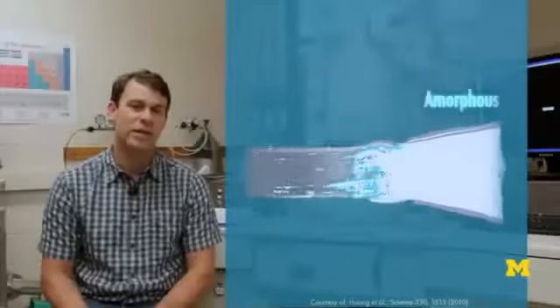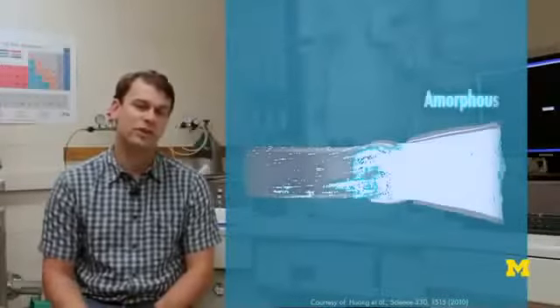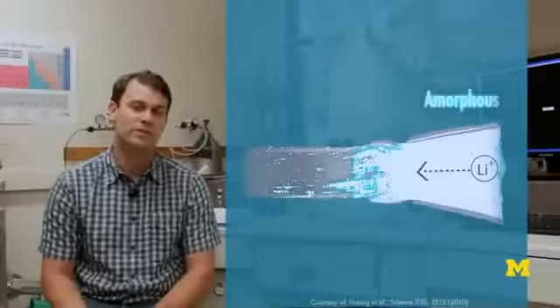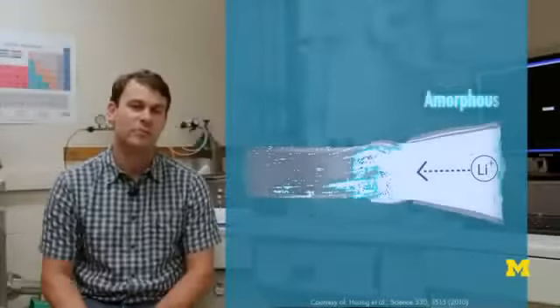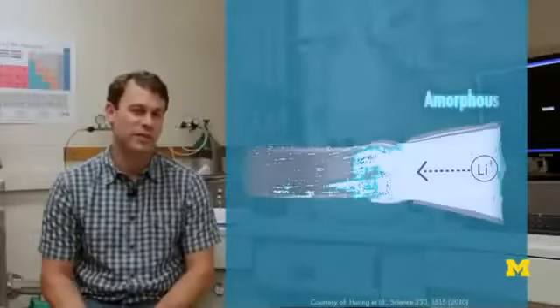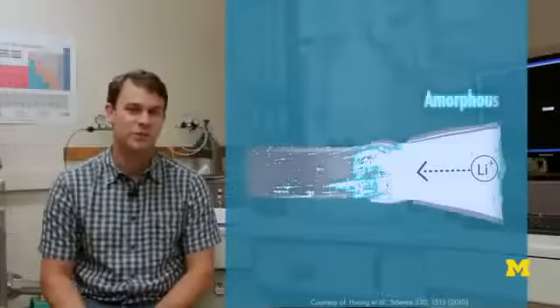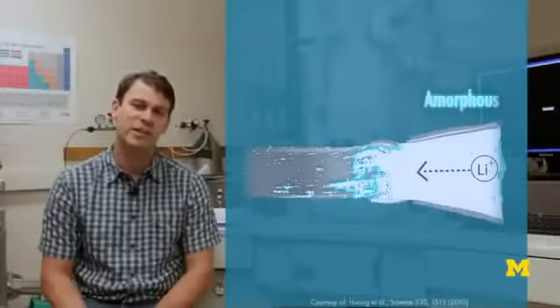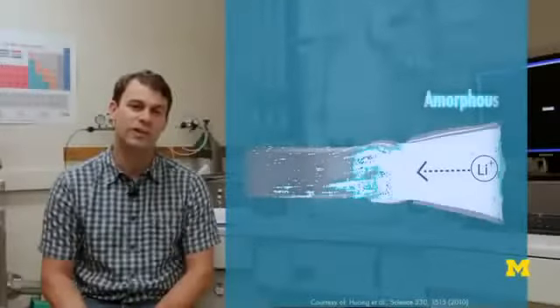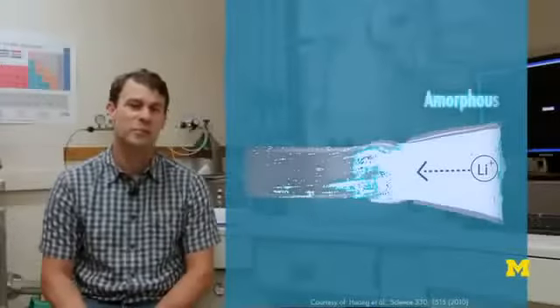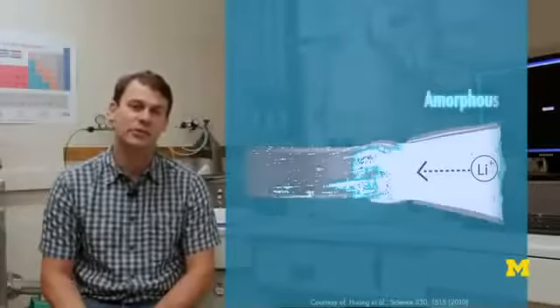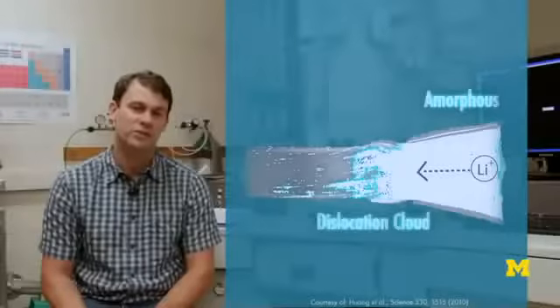That's because there's a volume change associated with the insertion of lithium. And what they're following is the recharging process, so the insertion of lithium into this tin oxide nanowire they're using in their model system. So to the left of that amorphous phase, you see maybe what looks like a tangle of spaghetti. That's where things really start to get interesting, because that's a reaction front that involves the nucleation and emission and gliding of crystal defects called dislocations. So those can be observed directly in this experiment.